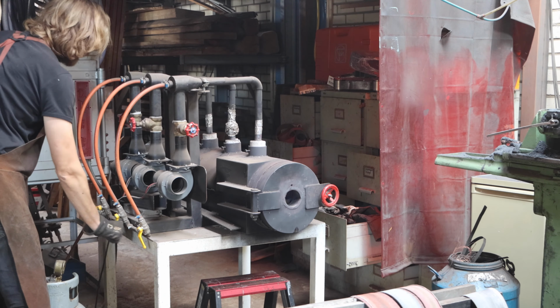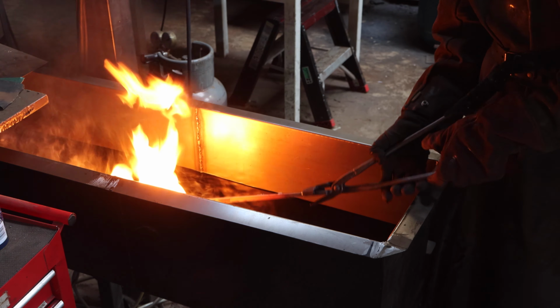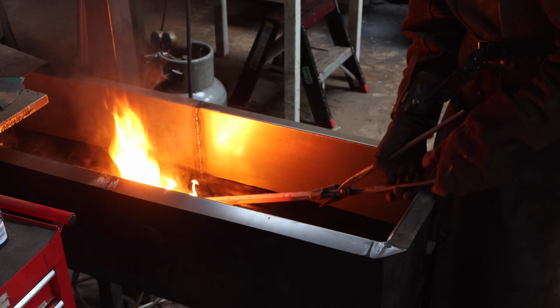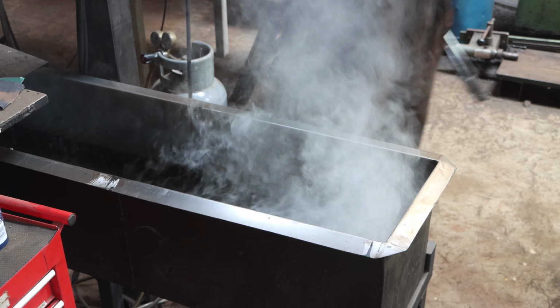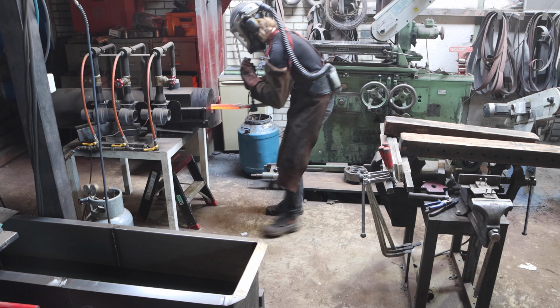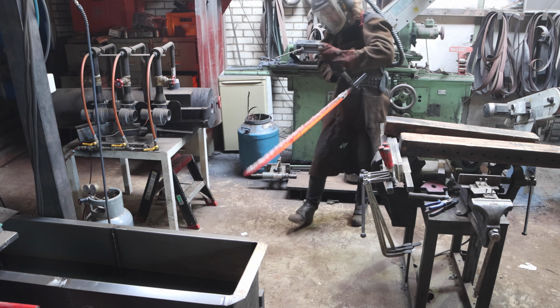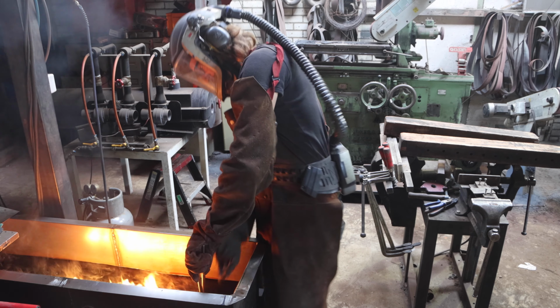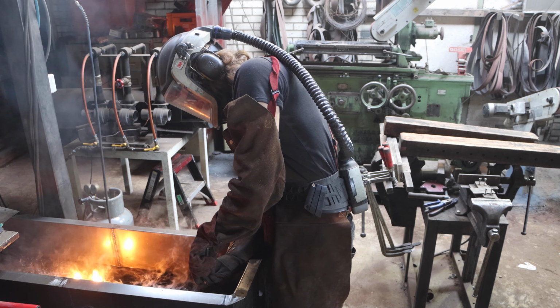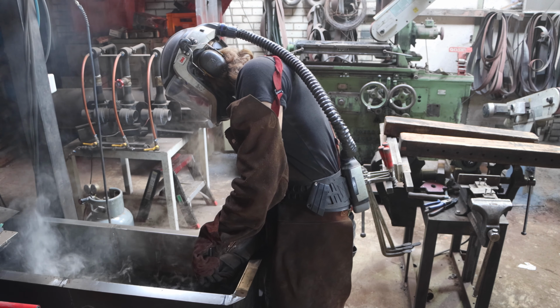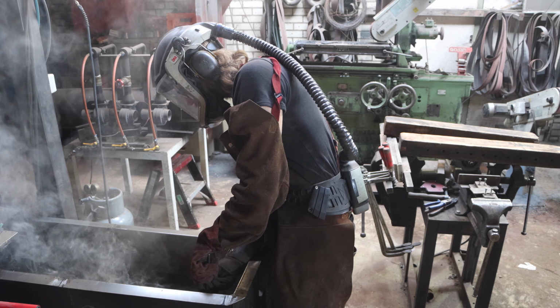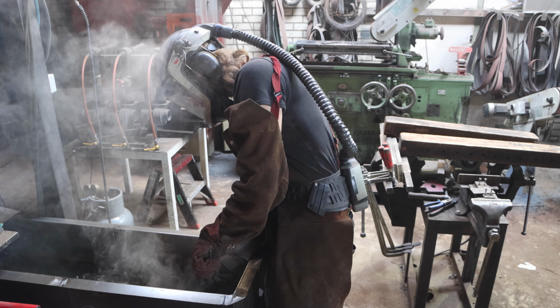A metal strip is used to heat up the oil. This oil is a very fast oil, around the same speed as water, but less likely to cause the sword to break or warp. Preheating the oil also helps evening out the initial shock. The blade has to be around critical temperature, red hot, preferably an even red. The hardening temperature completely depends on the steel type, also the chance of creating a Hamon or hardening line.